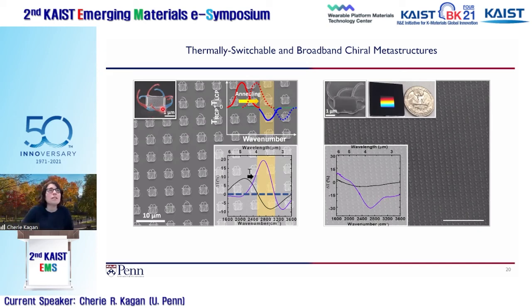And what you'd expect then is that the shorter ones would be at higher energy, or a larger wave number, than the ones that were red, and they would have opposite signs of their difference in transmission between right and left-hand circularly polarized light. So the red arms would give a lower wave number, positive, for example, difference in transmission, and the shorter ones would give you a higher wave number, but also a negative sign in the transmission. And so that's what we see. We can create positive and negative changes in transmission at different spectral ranges.